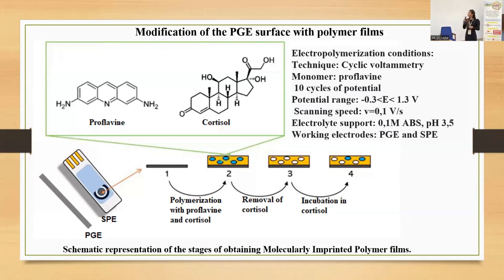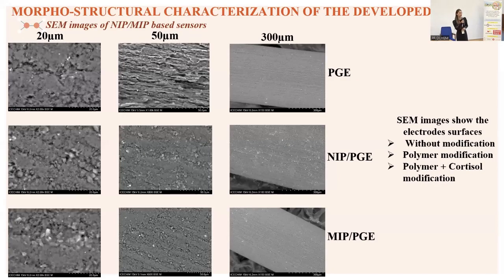So the synthesis took place by electropolymerization method in absence and in presence of cortisol by using proflavine as monomer. After the polymerization with proflavine and cortisol, the removal of the compound took place, and the specific cortisol gaps were created in the polymer film. A further incubation in cortisol would fill some of them with the specific molecule. The scanning electron microscopy images show the electrode surfaces without modification and with modification by polymer and polymer containing cortisol. In the first case, for the unmodified electrodes, the roughness of the surface was high, while in the case of the modified electrodes, a uniform distribution of polymer can be observed.